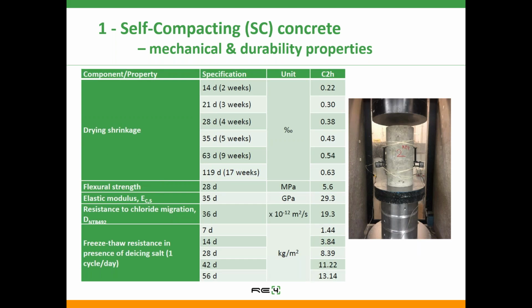Mechanical and durability properties of all the concretes developed have been determined to ensure that they are compliant with all the relevant standards. So the table shows the drying shrinkage of the concretes, the flexural strength, the modulus of elasticity. Chloride migration tests were carried out, as well as freeze-thaw resistance in presence of de-icing salts. So the full range of certification tests were done.